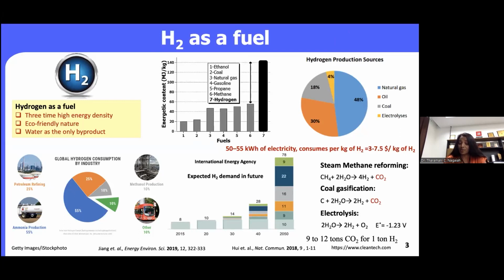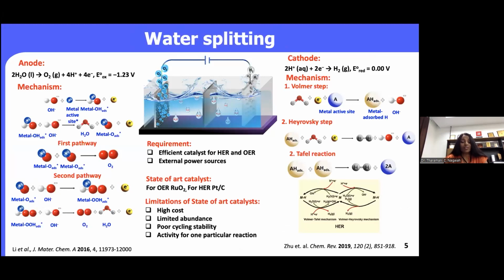To produce 1 ton of hydrogen, we are releasing 9 to 12 tons of CO2 into the environment, and only the 4% is one of the green approach. So in electrochemical water splitting, we have the anodic oxygen evolution and also the cathodic hydrogen production. It depends on the thermodynamic potential, which in this case is about 1.23 V. Depending on the pH of the media, the mechanism varies here, especially for hydrogen, which follows the Volmer step, the Heyrovsky step, or the Tafel reaction, or a combination of the Volmer step and the Tafel reaction. However, to develop water splitting or to produce hydrogen, we need an efficient catalyst for both hydrogen evolution at the cathode and oxygen evolution at the anode.